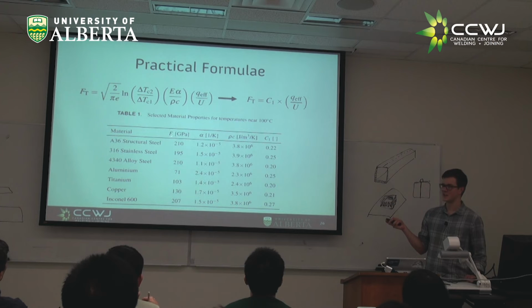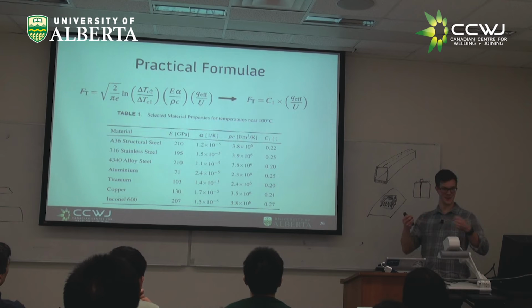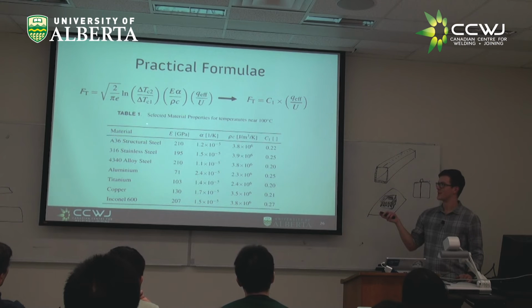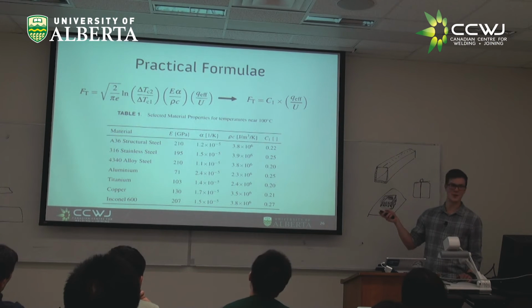Now, does anyone know what E is at a fundamental level? What is the elastic modulus? Stiffness? Right, it ends up being stretching of bonds. It's how stiff those bonds are. And what about coefficient of thermal expansion? It's how much the average bond length increases when you start to add some energy to stretch those bonds. So if you imagine that you have stiffer bonds, then typically this is going to be smaller, whereas if you have more flexible bonds, then this might be larger. So as this increases, this decreases.